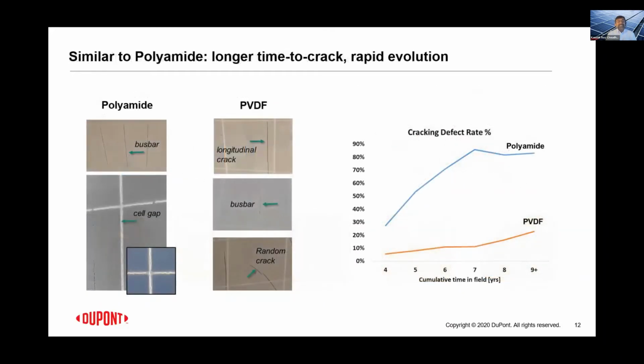Another reason that this concerns us a little bit is the nature of the defect that we are seeing in this material. It is very reminiscent of another material that has been known to be defective in the field, polyamide in this case. And if we even look at the trends of the defects between polyamide and PVDF, we always have seen this increasing trend with the number of years, showing that the material degrades more and more as we go through the number of years.